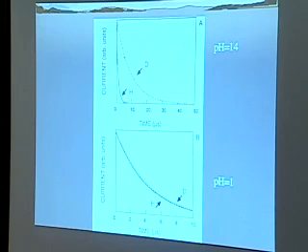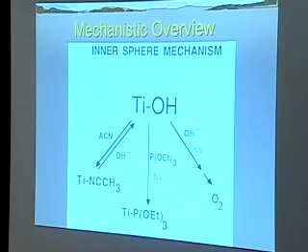So that argues that there must be a proton transfer in a critical step in this mechanism when we are in base, when we're oxidizing hydroxide, but not when we're in water. I was going to guess, actually, by the way, that it was going to go the other way around, because, of course, in the water, this is in acid, we're putting an extra proton or deuteron onto that water. It's really H3O plus that we're dealing with. So I thought if there was going to be a proton effect, it would be here, not over here. But clearly, there's a proton transfer in the hydroxide case. That is the key thing.